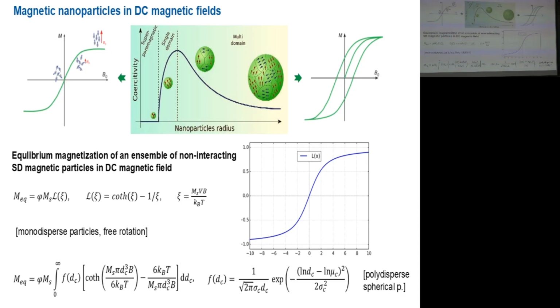But let us speak about the nanoparticles in the superparamagnetic state now. Let us speak about this region of the relaxing particles. And let us see the magnetization of the ensemble of such particles in a DC magnetic field. The magnetization will be described by the Langevin function. You have surely heard about this function. There is a parameter given by the spontaneous or saturation magnetization, by the volume of the particle, the magnetic field, and again the thermal energy. So this is the typical Langevin function, and of course there is some rescaling to the spontaneous magnetization and rescaling to the content of magnetic particles in the system.